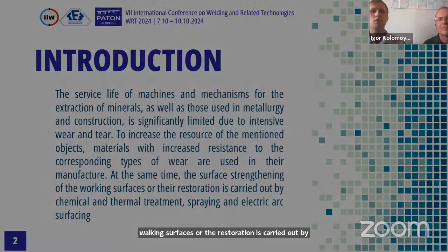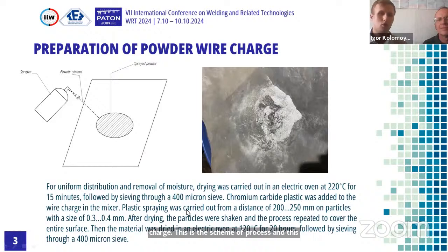Here we see the process of preparation of the powder wire charge. This is the scheme of the process, and this is the complete mixture. For uniform distribution and removal of moisture, drying was carried out in an electric oven at 220 degrees Celsius for 15 minutes, followed by sieving through a 400 micron sieve. Chromium carbide plastic was added to the wire charge in the mixer.